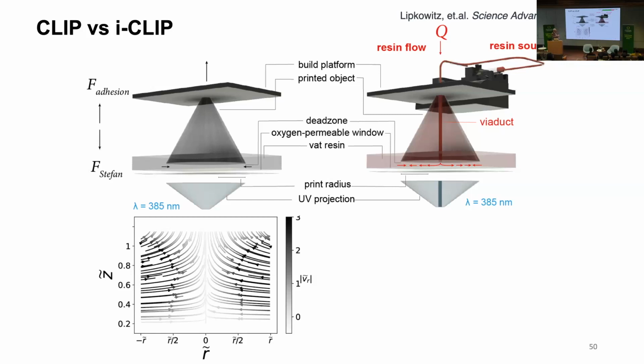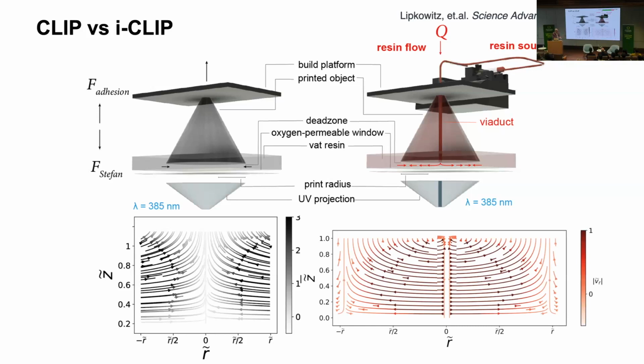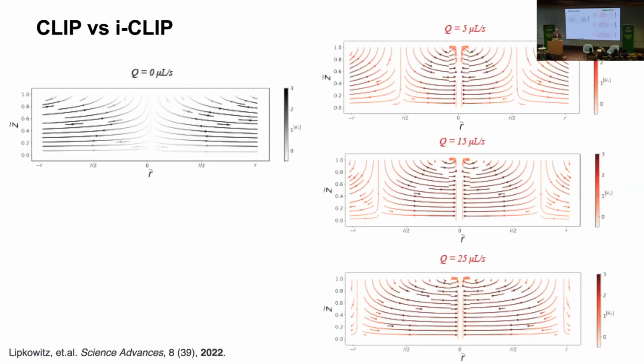So we thought, couldn't we inject the resin through the part, through a microfluidic channel that was in the design of the part to begin with, and mechanically push resin into that gap and speed up the replenishment of the resin using mechanical flow? So now we have resin coming through the part. And this works like a champ. And you can have some of the resin being fed from the channel and some of the resin coming laterally. You get to choose how fast you're feeding the resin. The resin comes in different directions.